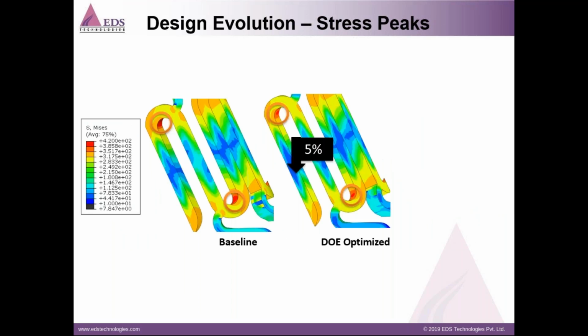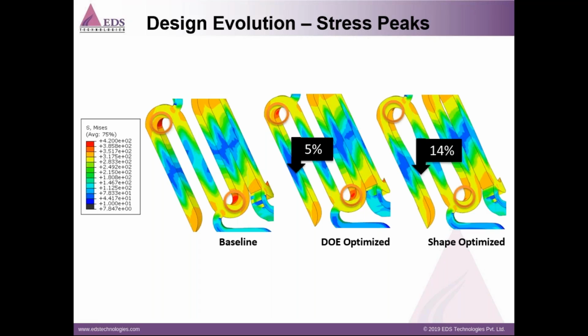We are also going to look at the fatigue hotspot as well as stress factors here. Let us see how it leads to the overall stress and the fatigue factor. The parametric optimization led to a 5% reduction in the stress peaks, and the shape optimization leads to a 14% reduction in the maximum stress compared with the initial baseline design. So over two steps, parametric optimization gives 5%, and then shape optimization, which is non-parametric optimization, gives a further improvement on the stress peaks.